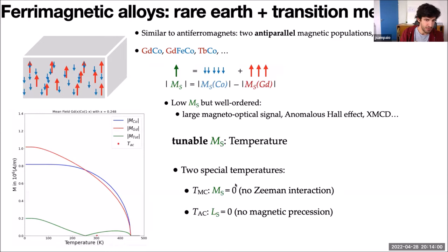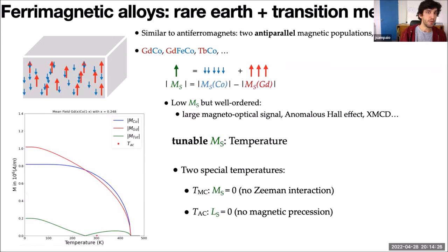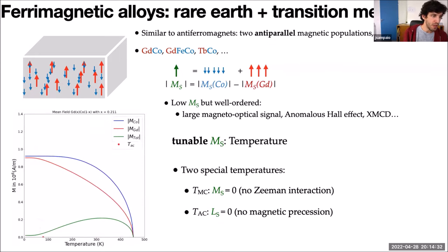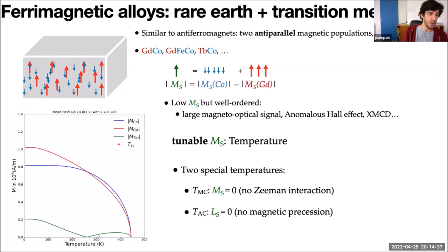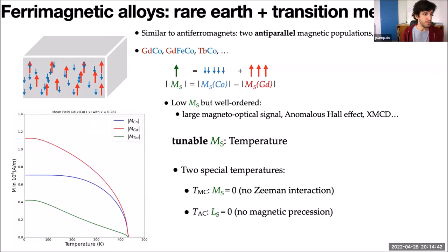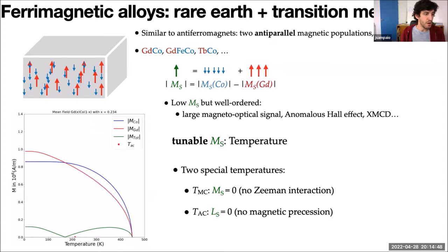What is very interesting in this family of alloys is that you can change the net magnetization by changing the temperature. As you heat up, the magnetization of gadolinium decreases faster than that of cobalt, because they have different magnetic natures. At the magnetic compensation temperature, both magnetizations compensate and the net magnetization is zero. There is also the angular momentum compensation temperature, where the angular momenta are balanced rather than the magnetizations, occurring at a different temperature. You can also shift these compensation temperatures by changing the relative amounts of cobalt and gadolinium in the amorphous alloy.